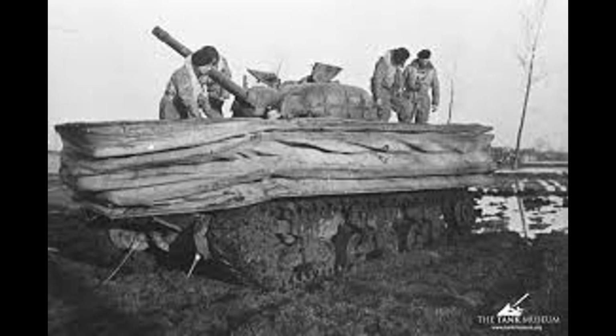In the cold water of the English Channel, this ductility made all the difference. Standard rapid-cooled welds behaved like glass in near-freezing temperatures. They would crack under stress. Ridley's slow-cooled welds behaved like metal. They would deform slightly but remain intact. By the first week of June, 1944, nearly 700 Sherman DD tanks had been converted using the modified welding technique.